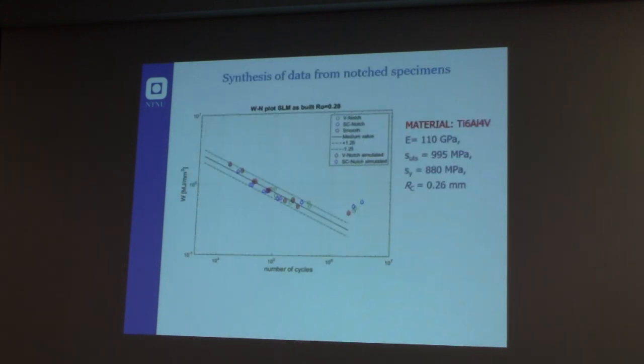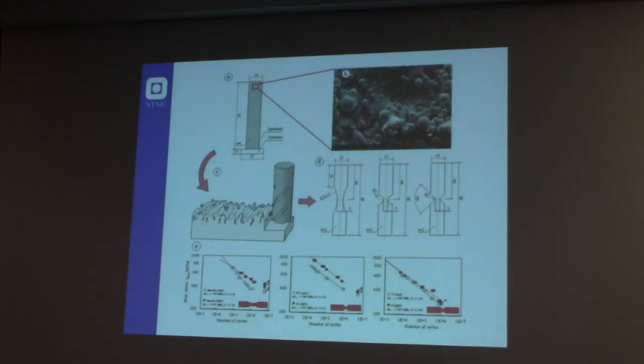And we also changed different materials, so we are working on titanium. Of course, the process is affecting the surface roughness a lot, and what is also important to consider is the residual stress effect that you have close to the surface for these components, for these materials. But I think with post-treatment, that can be mechanical or HIP, hot isostatic pressing, you can actually reduce the level of porosity, and you can also make post-treatment for releasing the residual stress, so you can actually apply very easily the concepts that we have developed before.